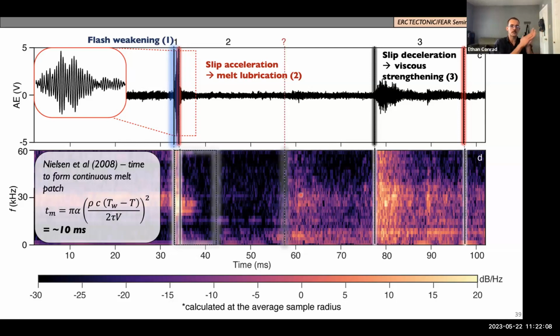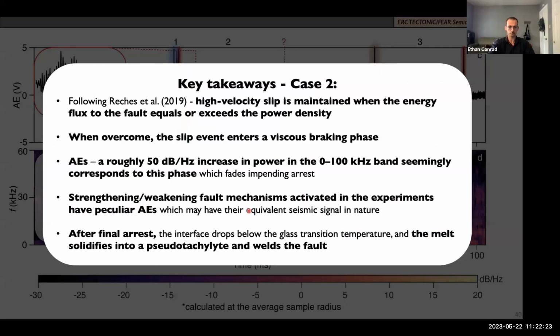But using an equation from Nielsen 2008, we can think about the time needed to form a continuous melt patch, and that's shown in this light gray here. So the melt is forming here, and then you have this continuous melt patch within this window of silent acoustic emissions. So the key takeaways here are that following rupture, the high velocity slip is maintained when the energy flux equals or exceeds the power density. When this is overcome, you enter a viscous braking phase. And this viscous braking phase corresponds to a roughly 50 decibel per hertz increase in power in this band that we were looking at.